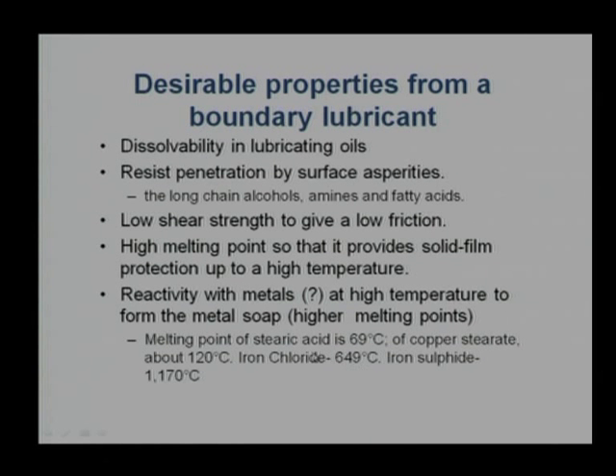This is an example, it shows stearic acid, which is a boundary additive. It has a melting point around 69 degrees centigrade when we are talking about it in the absolute, without any reaction. However, when it reacts with the copper surface to form copper stearate, it melts at 120 degrees centigrade, which is relatively higher compared to 69 degrees centigrade. Similarly, if there is chloride or chlorine available as a chemical additive, which goes hard with chemisorption, then iron chloride, which is in solid form as a sacrificial layer, has a very high melting temperature, 649 degrees centigrade.